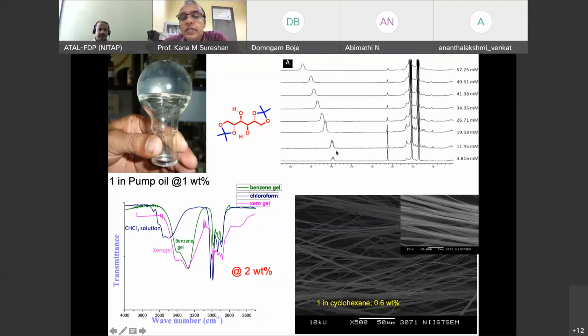Now, on the right-hand side, what you see is the concentration-dependent NMR in a gelling solvent. Benzene D6, or benzene also, this same molecule gels. With increasing concentration, you can see I have changed the concentration from 3.86 to 49 millimolar on top. So what you see here is the OH signal. These two OH signals appear here at low concentration. But on increasing the concentration, you can see there is a downfield shift of the hydroxyl signal. This says that this is an intermolecular hydrogen bonded self-assembly. So this is almost at the gel state. You can see there is also line broadening because it's becoming more and more viscous, and finally it's a gel. Then you won't get a good NMR. So you can clearly see the shift that says that it is intermolecular hydrogen bonding.